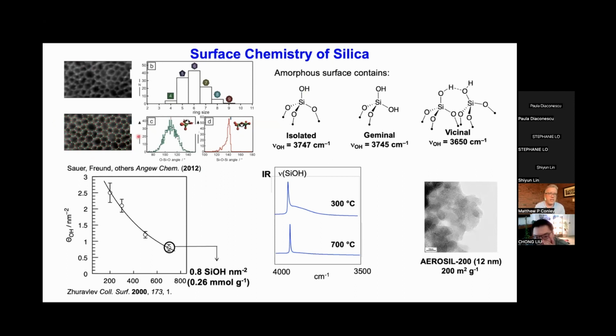So these are surface images with DFT modeling by Sauer and Freund, where they grew vitreous silica on a ruthenium surface. And so this is a silica surface that really is just comprised of Si-O-Si linkages. You get a variety of ring sizes, from highly strained 4-membered rings to the dominant, less strained 6-membered rings that have various angles associated with them. So we know we're going to have a silica surface that has a whole bunch of Si-O-Si bridges of various ring strains, and some of these can play a role in chemistry. But from an organometallic perspective, what's going to be doing most of the work are the leftover silanols that come at the terminated surfaces of silica.